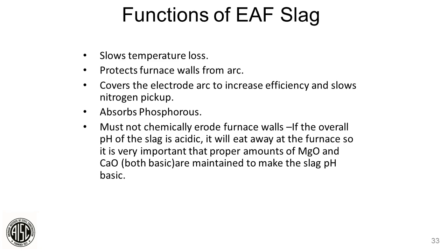There are some practical needs, and there are also some needs of just the slag processing of the steel. So you've got to slow the temperature loss because you can't have heat radiating out all over. It protects the furnace walls from the arc, because the arc plasma is extremely hot, high energy. We have to control that. And it covers the electrode arc to increase the efficiency and slows down nitrogen pickup. Now we talked about nitrogen before. But actually what happens is ambient air flows through the arc plasma, the nitrogen gets stripped and actually gets absorbed into the steel. So we get so much, but we can't have too much. We've got to control that.